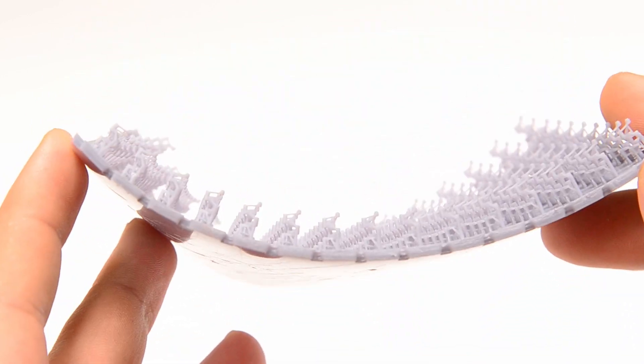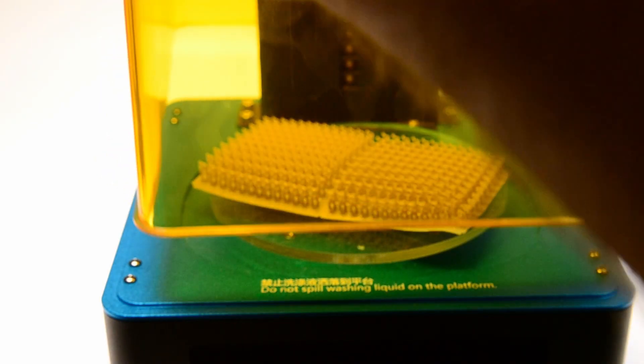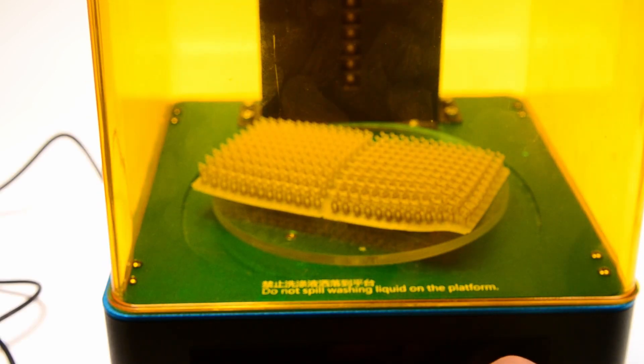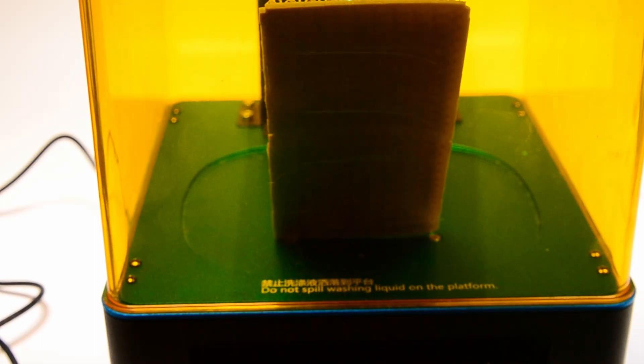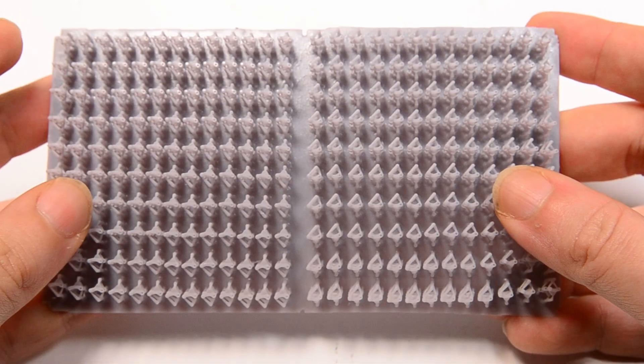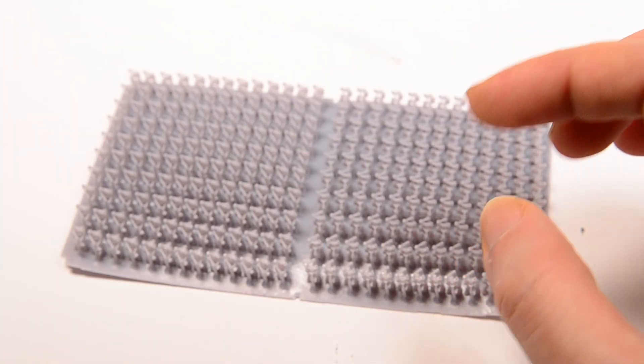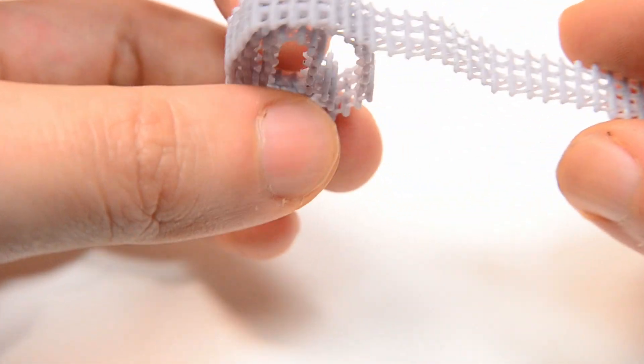These tracks are still tightly crammed together and the density of the part placement is directly related to how well you can clean your parts. At the moment none of the holes are clogged anymore and no residue stays on the part, but compared to common recommendation, the washing time is very high in this case. After washing the parts I let them dry wrapped into a kitchen towel, placed in a dark box. Exposure to sunlight or UV light would otherwise cause the raft to warp extremely. Post curing is done on the same machine, exposing the printed part to high intensity UV light multiple times at multiple angles.